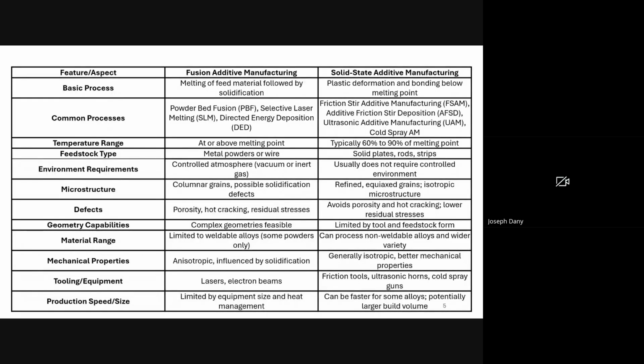When we compare the temperature ranges between the two processes, fusion processes have to run at or above the melting temperature, whereas solid-state processes usually operate between 60 to 90% of the melting point. That is 0.6 to 0.9 of the melting temperature, without actually causing melting. In terms of feedstock types, fusion additive manufacturing typically uses metal powders or wires, while solid-state approaches rely more on solid rods, plates, and strips. Now, about environmental requirements, fusion processes usually need a controlled atmosphere such as vacuum or inert gas to avoid oxidation. But solid-state additive manufacturing usually does not demand that kind of strict environmental control. If we talk about microstructure, fusion processes tend to produce columnar grains and can show solidification defects, whereas solid-state processes are known for producing fine equiaxed grains with a much more isotropic microstructure.